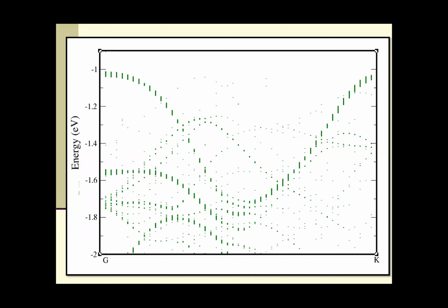Essentially what I show over here is that I have taken each of the supercell bands and projected it onto the K point, where this gamma to K is along the primitive cell. I find out what the weight is at each of these points, and the width of each of these bands represents its contribution at that point. Indeed, what I see first is that even in spite of having a 1500 atom very large unit cell, I have a band structure associated with it.